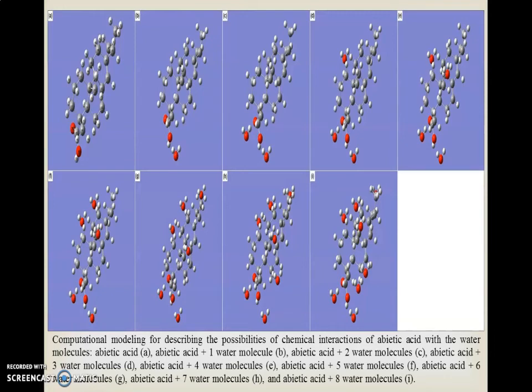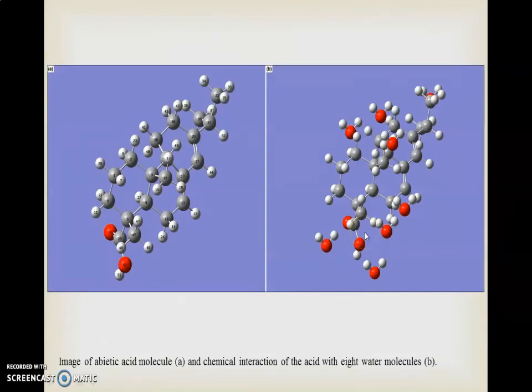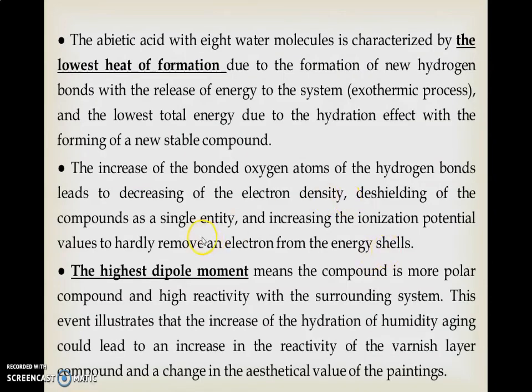Also, we studied the outer varnish layer upon water uptake, with abietic acid as the main component of the pine resin, with 1 water molecule, then 2, 3, 4, 5, 6, 7, 8. Abietic acid with 8 water molecules showed the lowest heat of formation due to formation of new hydrogen bonds with release of energy to the system, an exothermic process and the formation of a new stable compound. And the highest dipole moment means that the compound becomes more polar, more reactive, and interacts more with the surrounding material and changes the aesthetic value of the painting.